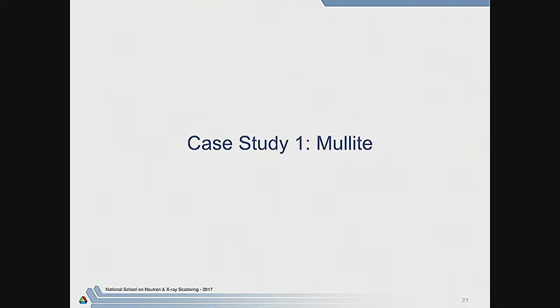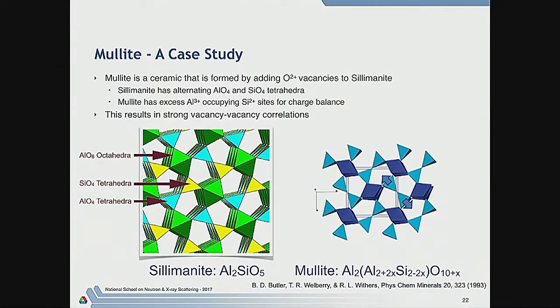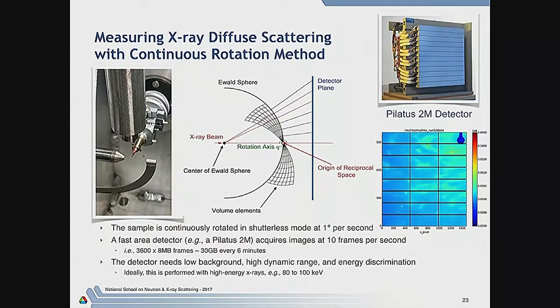Okay, so I wanted to give one quick case study, which is mullite. Mullite is an alumina silicate, which has all of these tetrahedra coupled with these octahedra. These tetrahedra are AlO4 or SiO4 tetrahedra. But if you put in excess aluminum, then you're going to generate vacancies on these bridging oxygen sites here. And what happens when you do that is that the neighboring cations relax away from the vacancy and produce another tetrahedron here. So you get these sort of tri-clusters around each vacancy. And that's a motif that was identified from powder diffraction, which showed on average that these extra sites existed. How would we measure this?